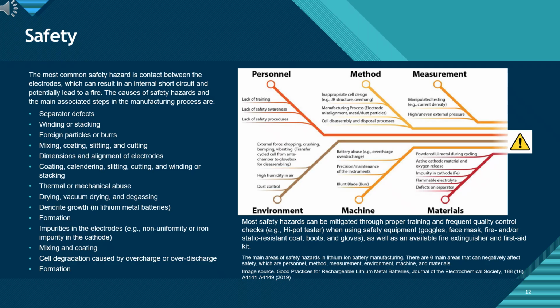Even small metallic contaminants, such as iron particles from worn tooling, can penetrate the separator during cycling and trigger a short. Process drift in coating thickness, calendering pressure, or electrode dimensions can also reduce the safety margin between layers. In addition, thermal or mechanical abuse, overcharge or overdischarge, and the gas generation stages of drying, formation, and degassing introduce additional risks if environmental controls are insufficient.